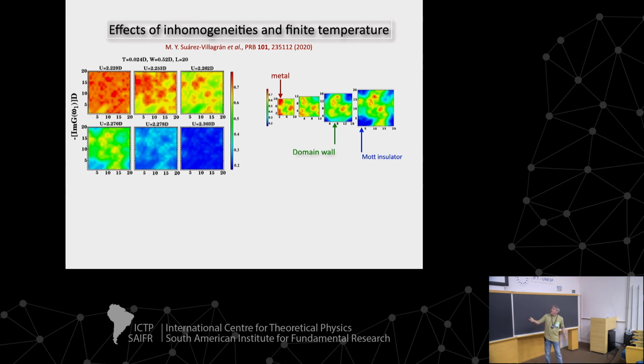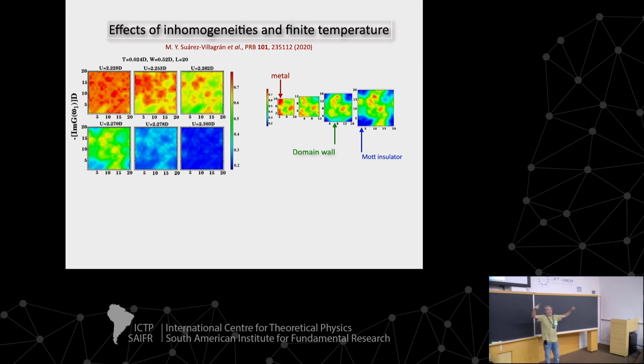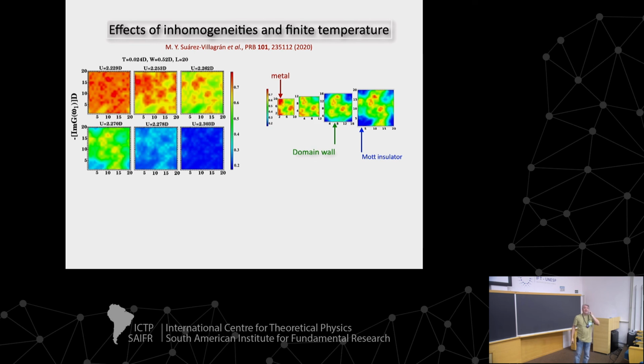So we see, for instance, this is as a function of size. So you start with a metal here, then you start increasing. That metal is still there, but then you start getting the other phase. If you go further, you're going to generate the other bubble, and in the thermodynamic limit, there is no transition. This is an effect of finite size in 2 dimensions. In 3 dimensions, there is a transition in the universality class of the random field Ising model. If you put in the U, it's a different universality class, not the random field anymore. Okay?